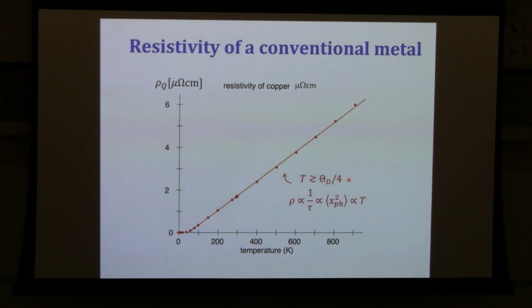So we understand well this very broad regime of temperatures where the resistivity grows linearly as a function of temperature. This is just a result of electron-phonon scattering. So the phonons are in the equipartition regime. The mean squared displacement of the ions of the metal is linear in temperature, and this is the reason why the resistivity grows linearly with temperature.